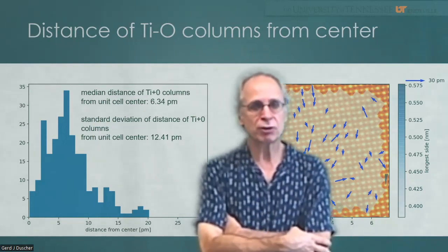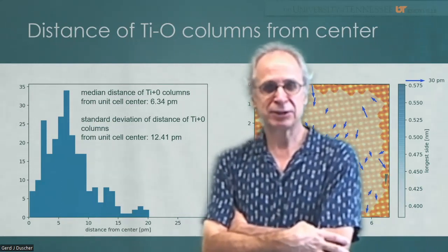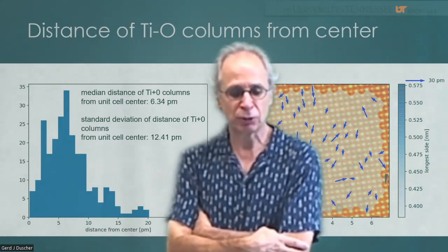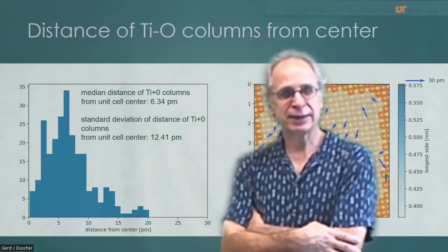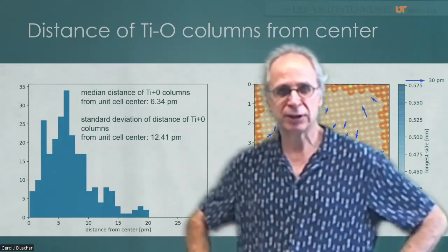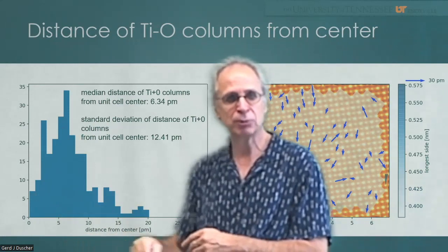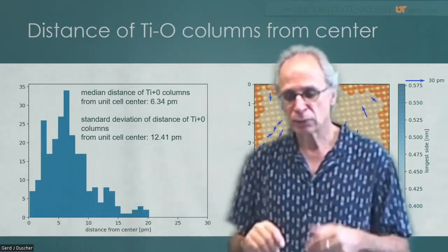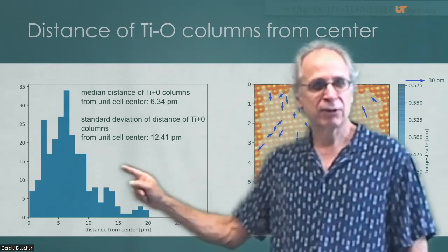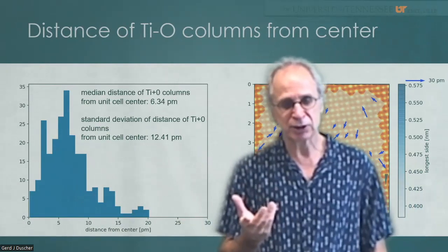It's actually not clear whether that is a materials property or not, right? So it's too small to call. On the other hand, we saw when we did it directly on the image, we had something like 2 or 3 picometer. So still okay. The standard deviation is 12 picometers, so again, subpixel accuracy.